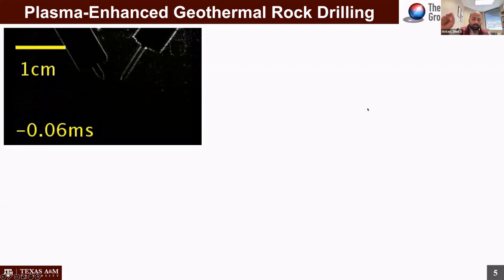Keep in mind the actual plasma is a pulse plasma. It's about 40 to 80 joules in this case. I forget which exactly. It's either 40 or 80. And it's generated very rapidly within 10 microseconds. It's not the fastest we can generate, but for this energy, it is close to the fastest we can generate. Think about this as lightning underwater.